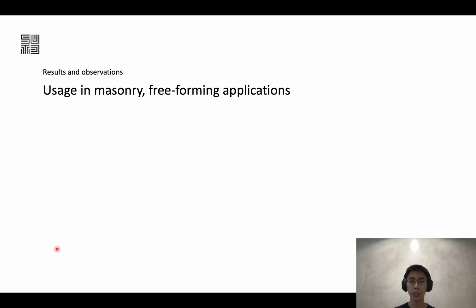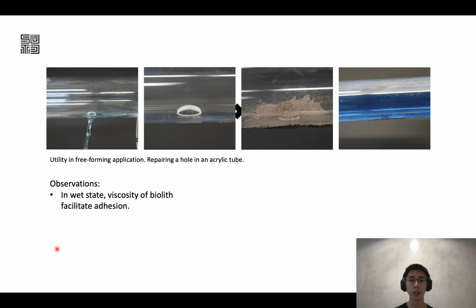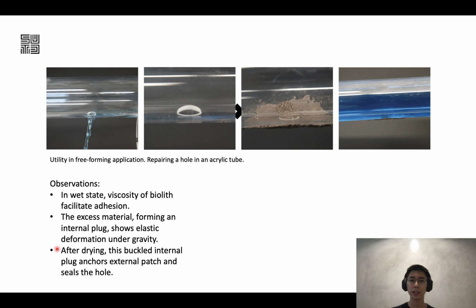Now, knowing that we can manipulate them in wet form, we move on to the next application, which is the free-forming application. Now here, what we try to do is use Biolith in a wet state to plug in and cap a pipe that's leaking. Now in its wet state, the Biolith is able to adhere to the surface of the pipe with excess material actually entering into the pipe and forming sort of an anchor because of elastic deformation under gravity. Now, when this patch is dry, this actually forms an internal anchor that seals the external patch against the acrylic pipe, and this effectively seals and holds water within this pipe and repairs it in the process.